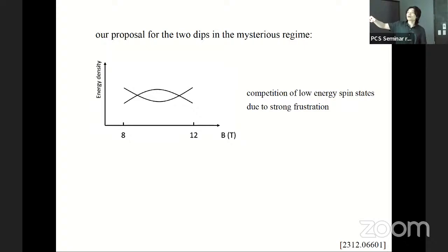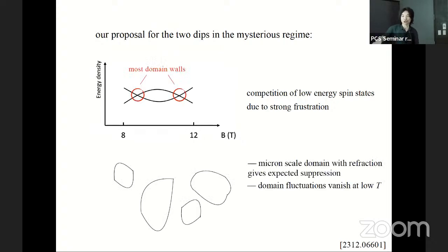So we propose that because this is a highly frustrated spin material, in the intermediate magnetic field regime, there can be some competition of low energy spin states because it's highly frustrated. And as you tune the magnetic field, you can imagine a scenario where the energy density of one state is lower for some magnetic field, but that of the other state is lower for some other magnetic field. You can imagine a scenario like this. And because they are competing low energy spin states at finite temperatures, there will be fluctuation of domains, right? Just like in an Ising model, there will be some formation of domains.